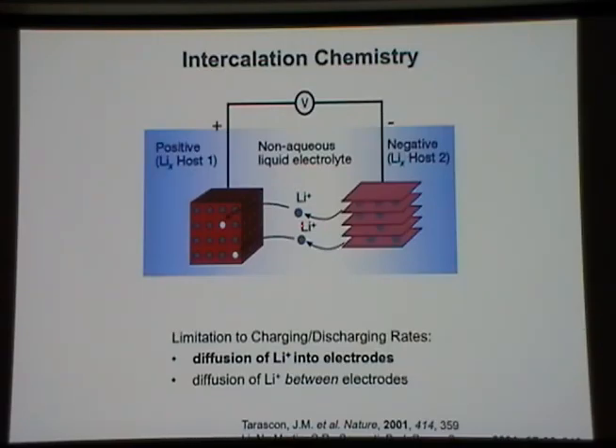What we're talking about is mechanical stress. There's another problem: when lithium gets to the surface of this electrode, what has to happen if I want to put more lithium in? The ones that are already on the surface have to move inside the electrode — the lithium on the surface has to diffuse in. This is solid state diffusion, which at room temperature is very slow. If we take this electrode and make it really small — nanoparticles, nanowires, or sheets — we essentially eliminate the solid state diffusion problem, because now the whole structure is mostly surface. Also, really small particles can dissipate mechanical stress more effectively. The first half of this talk is about diffusion of lithium into and out of electrodes.